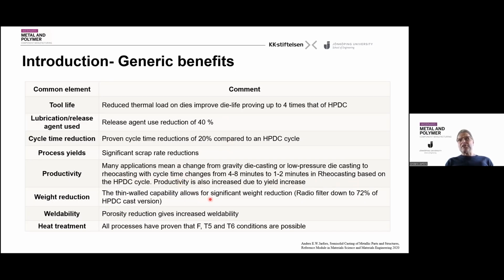And then you have the thin wall capacity, which is also important when it comes to weight reduction. And this is due to the fact that we have a shear thinning behavior in the material. And the shear thinning behavior allows you to better manage transitions from thick to thin sections. And because you have reduction of porosity, primarily because of the reduction of release agent, and that you have a partial solidification, you get weldability and heat treatability as cream on top.